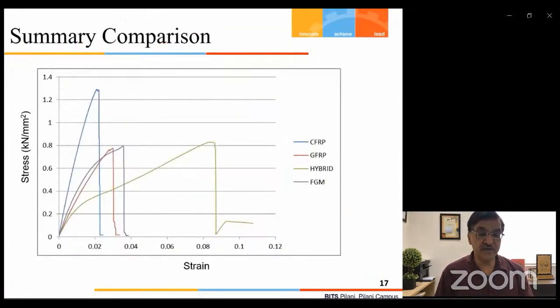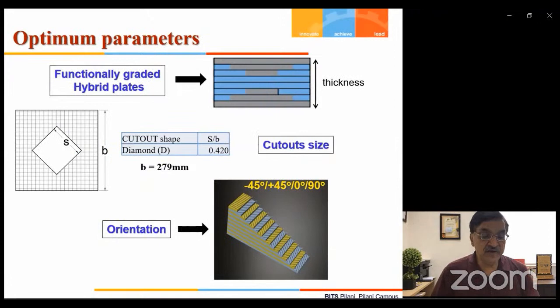Here is a summary comparison of the stresses and characteristics. We find that hybrid composites have a very good response, with reasonable strength and significant deformation capacity, whereas carbon fiber has high strength but very low deformation capacity. The functionally graded composite material has characteristics similar to glass fiber composite but slightly better strength and deformation capacity. Then for post-buckling strength evaluation, we have taken different sizes and shapes of cutout.